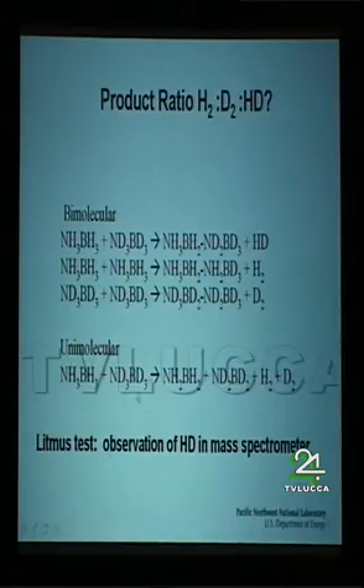So what we did was we can make this, or you can buy this from Aldrich, and we can deuterate the material or make deuterated material. And so the concept is to make a homogeneous mixture, solid mixture of a per-proteated and a per-deuterated species. If it goes by a bimolecular reaction, we should see all these different isotopes, HD, H2, and D2, depending on how well it's mixed, kinetic isotope effects. If it's a unimolecular reaction, we should never see the mixed isotope. It should just give you the polymeric species that comes off of there.